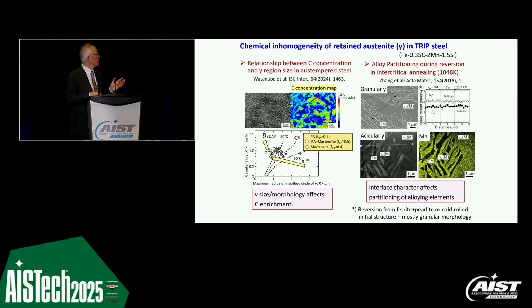We've been working for a while on defining the carbon enrichment in the untransformed austenite, for TRIP steel and also the reversion case. For the TRIP steel case, for the larger one, we have lower carbon content. For the finer one, particularly the film-like one, we can have higher carbon enrichment. But actually, in the microstructure, we have variation of the carbon enrichment in TRIP steel heat treatment. So austenite size and morphology affect carbon enrichment and phase stability of retained austenite.